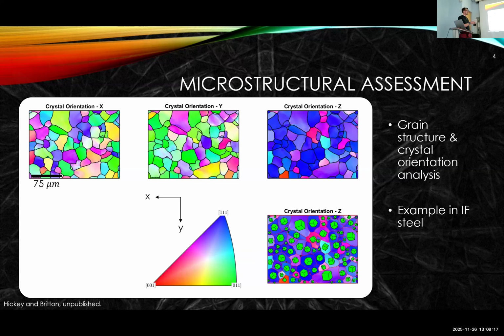We can also see that this has different shapes and sizes as different grains of different orientation, that could cause different mismatches in properties locally, which could be important if you're looking at fatigue of that material. You're looking at what happens under vibration, ultrasonics, etc. The scale bar is 75 micrometers. So we're mapping a reasonable size area of this material, and we're collecting that data and presenting it in a way that is, if you like, aesthetically pleasing, but at least enables us to interpret this data very quickly if we so wish.